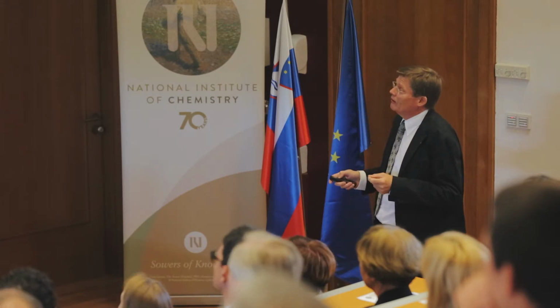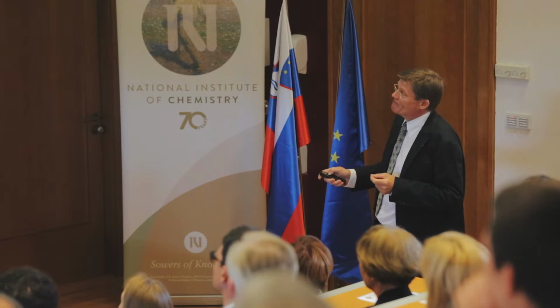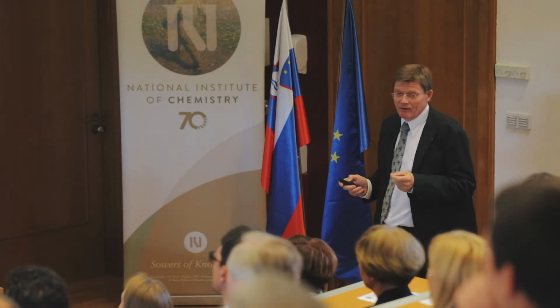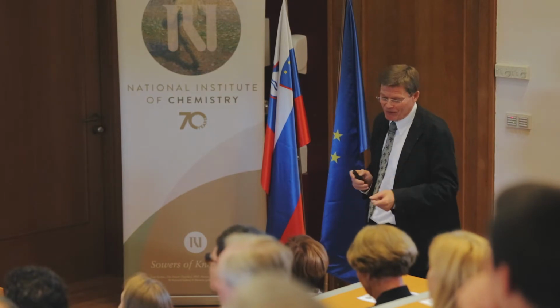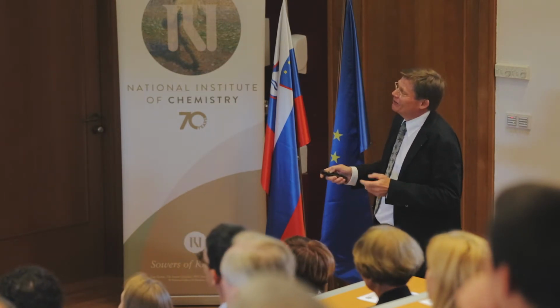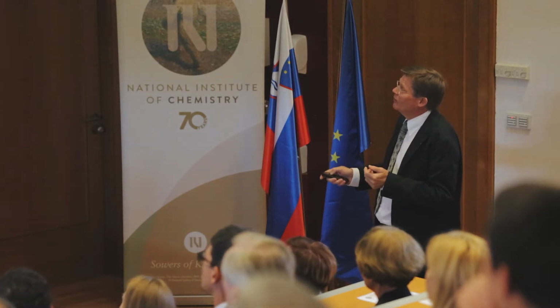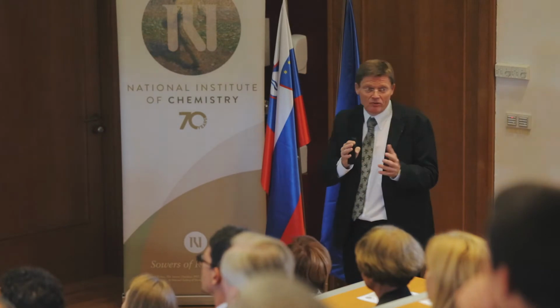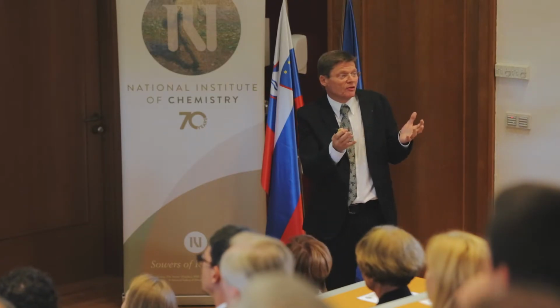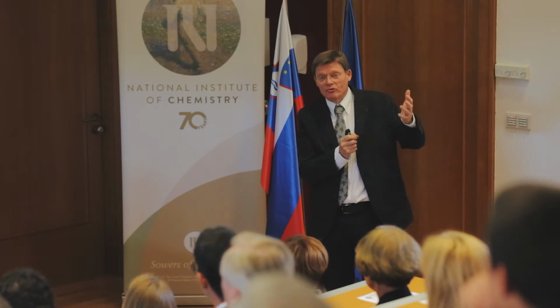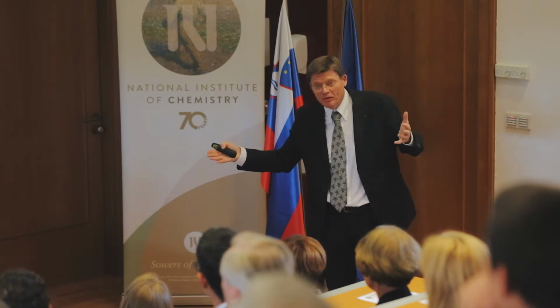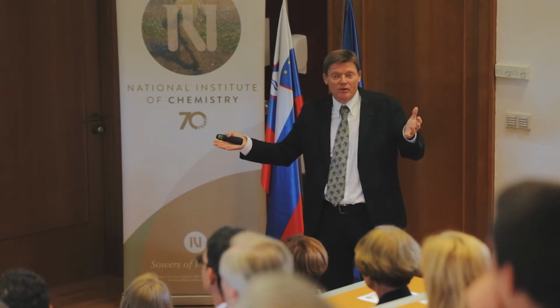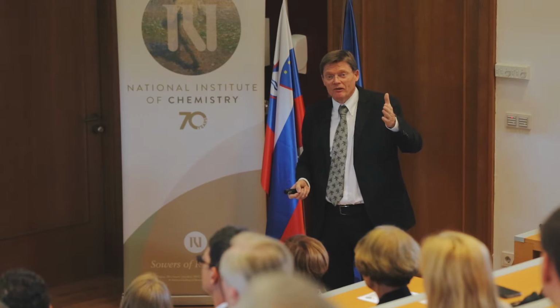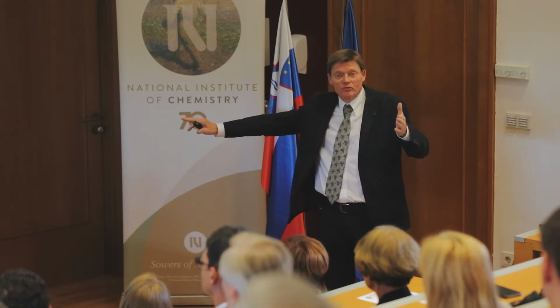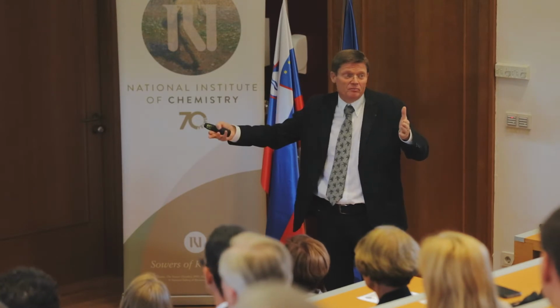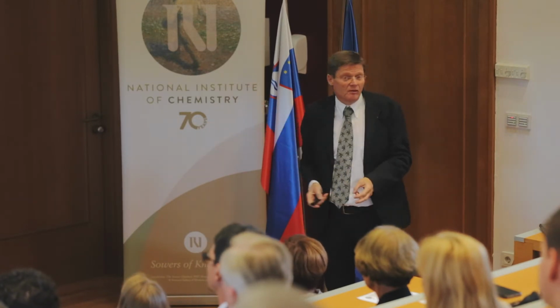It may look surprising. We had a technical experimental setup that was done by Jürgen Fleig. At that time, he was a fellow PhD student, a very good friend. He did this kind of experimental approach, and the evaluation was according to the equivalent circuit, and you get very nice results from amplitudes. It's a bit surprising. So how can, when you have maybe an absorption which is rate-limiting, how can this be mirrored in impedance spectroscopy? That's very strange. But it's simple, because when your absorption step, for example, is very sluggish, the current that you can draw through the electrolyte is very small. So it must be expressed electrically as well. And this is done by this chemical capacitor.